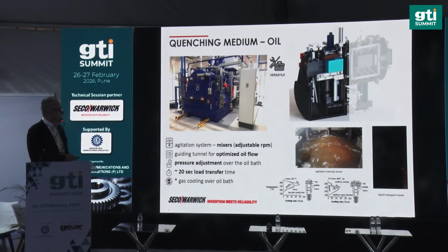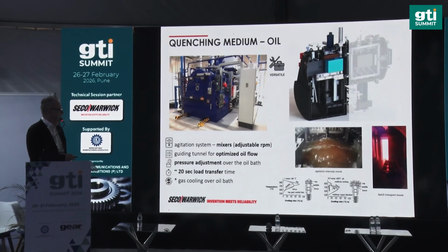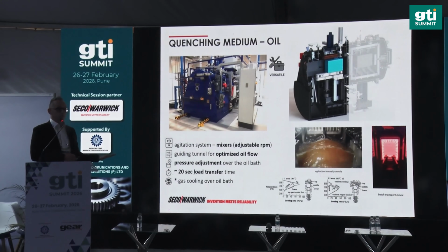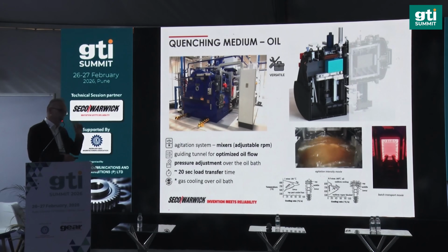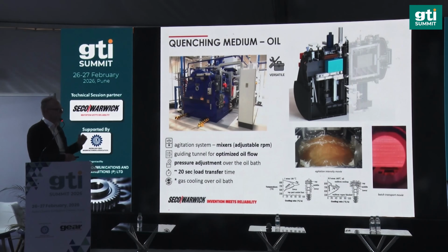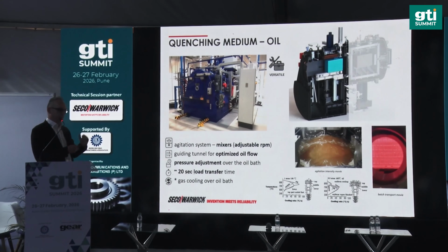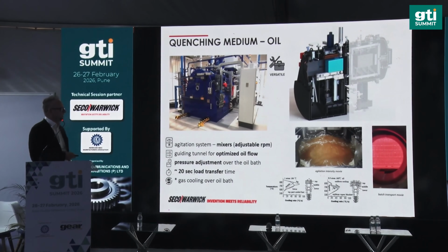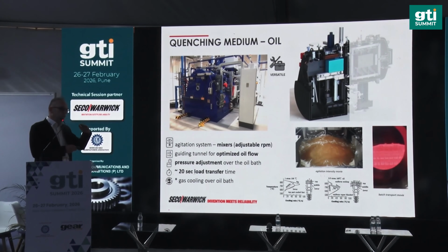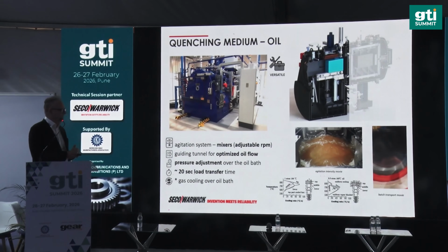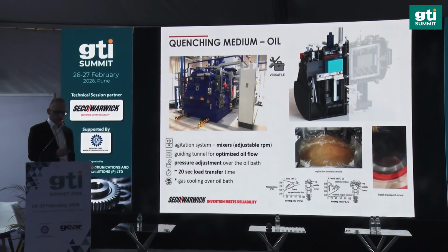Yeah, as I mentioned, if not high pressure gas quenching, then oil quenching. And also in oil quenching, with the vacuum oil quenching solution, you can also optimize the distortion, because you can play with the pressure over the oil bath. Due to the design of the furnace, you can play with that. By reducing the pressure, you actually reduce the intensity of oil quenching during the hardening procedure. So this is an additional option which you cannot get from typical atmosphere oil quenching technology.